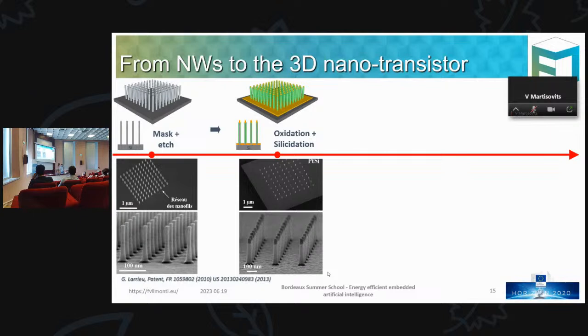That allows to clean the tip and the bottom of the nanowire arrays. And then we deposit platinum and treat it thermally. And this will allow to create PtSi heads on the tip of each nanowire and also at the bottom. And so this way we have in one step the source and the drain prepared. Then